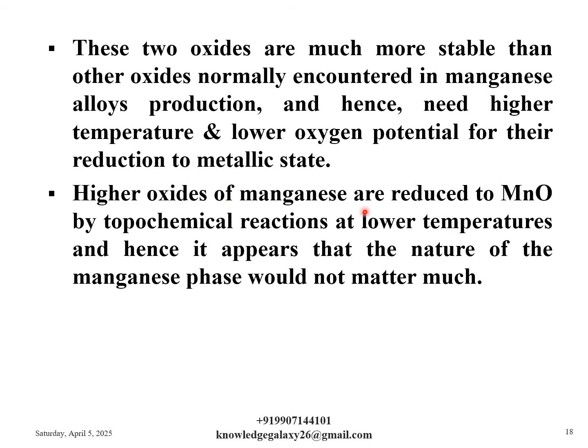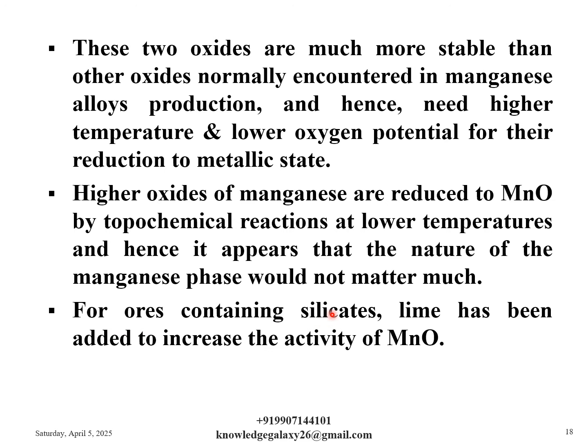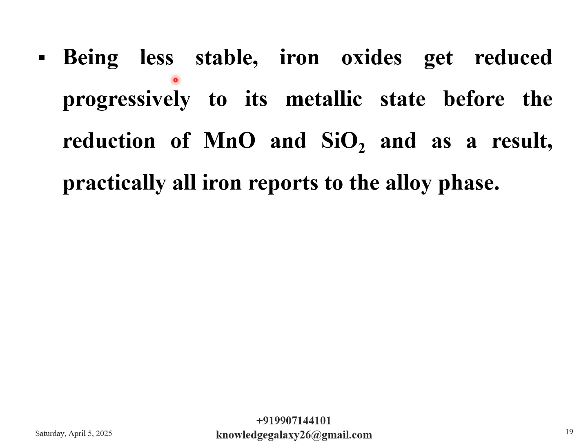Higher oxides of manganese are reduced to MnO by topochemical reactions at lower temperatures, and hence it appears that the nature of the manganese phase would not matter much. For ores containing silicates, lime has been added to increase the activity of MnO. Being less stable, iron oxides get reduced progressively to their metallic state before the reduction of MnO and SiO2, and as a result, practically all iron reports to the alloy phase.